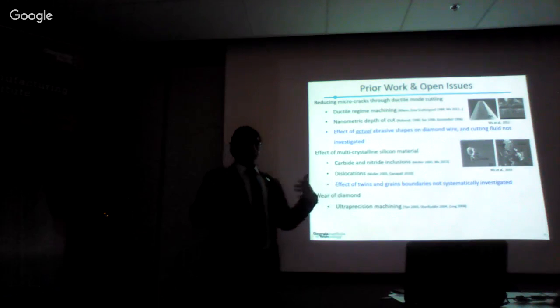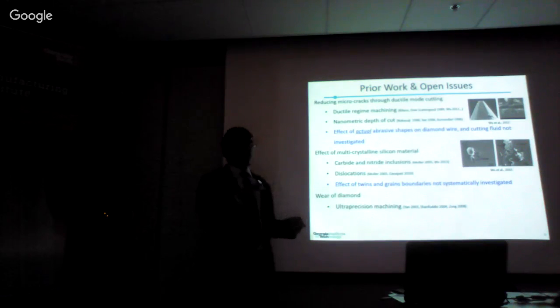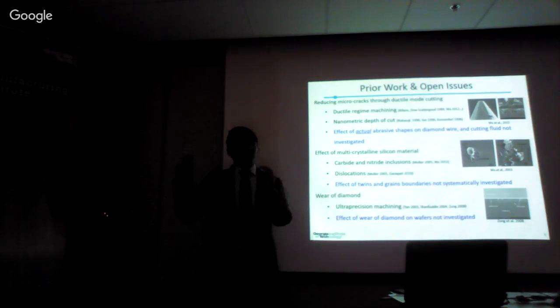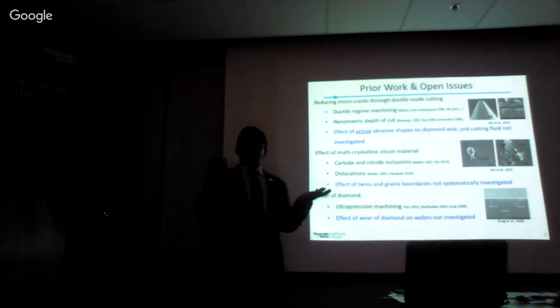Diamond wire sawing is a relatively newer process compared to loose abrasive slurry sawing. And the wear of diamond in diamond wire sawing had not been looked into. Most of the prior work had been in diamond turning experiments, like ultra precision machining for making lenses. And here you see some work which shows the wear of the diamond tool used in turning experiments. But the effect of wear of the diamond on the actual diamond wire on the silicon wafers had not been looked into. So in my PhD, I look into the effect of diamond wear on the silicon wafer surface and